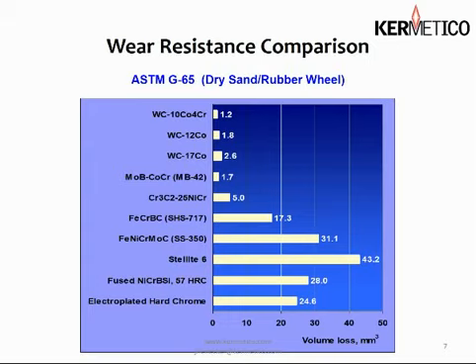Fuse coating, 57 Rockwell C, is 28 cubic millimeters lost compared to our 1.2. But here's the real yardstick: WC-10Co4Cr, 1.2 cubic millimeters lost. Electroplated hard chrome, 24.6 - that's over 20 times the wear rate of our WC-10Co4Cr coating.